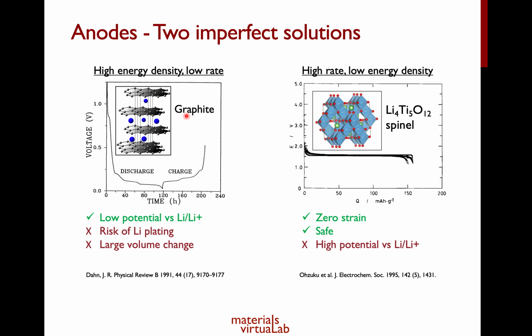Just to show you how old these anodes are, I've deliberately chosen the very early works demonstrating their application as anode. Graphite was basically proposed back in the 1990s, and this is work that was done by Professor Jeff Dahn. The reason why graphite is such a good anode is because of its very low potential versus lithium plus. What this means is that when you use graphite as an anode, you do not lose a lot of energy density relative to the lithium metal. And so you can make very high energy density lithium-ion batteries using graphite anodes.